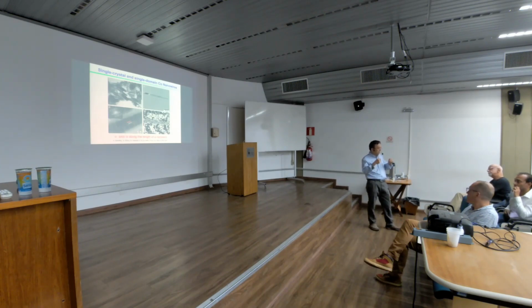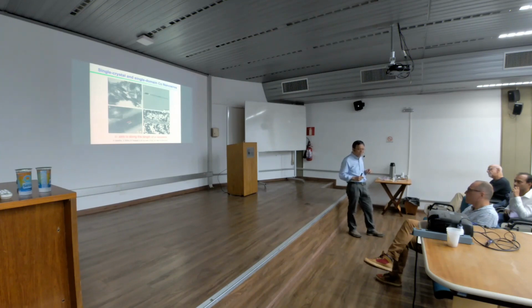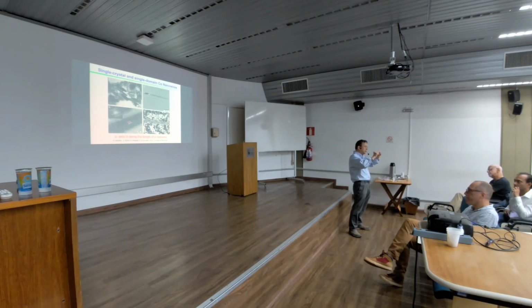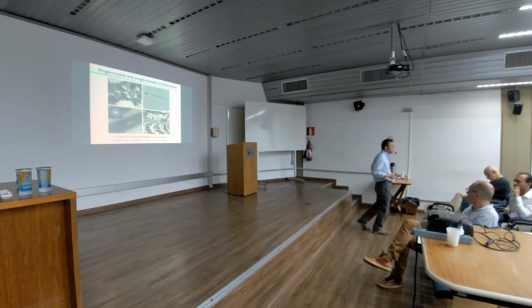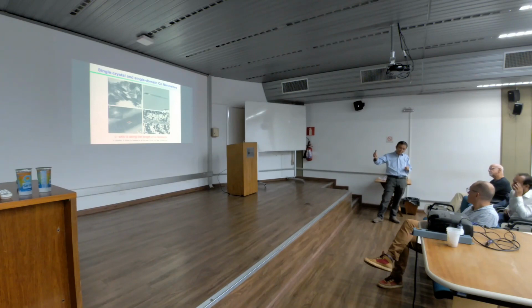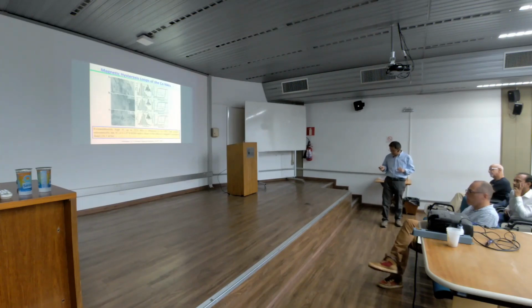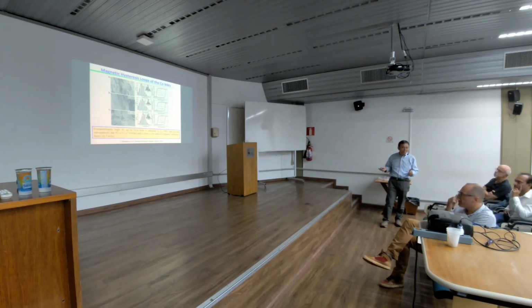For 70 years, in my opinion, people were never able to obtain samples which are absolutely homogeneous. There are always defects, because the smallest size, as I told you, is microns or even millimeters. You could not go even smaller. If you could not go even smaller, then you're not homogeneous. So the conditions by Brown were never met. Now we think we meet the conditions. You see, you measure coercivity immediately when we went down to 8 nanometers, which is the smallest diameter we could reach. We tried further, but we could not reach smaller.